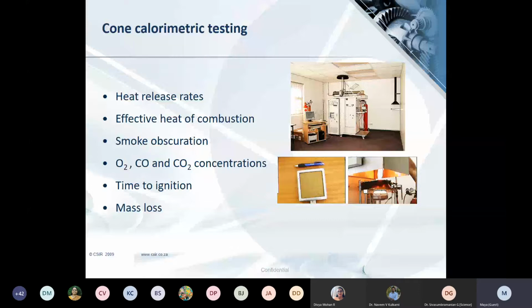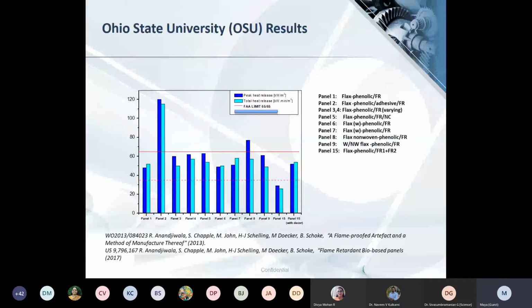So these are the flammability results from the OSU testing. And this graph shows the peak heat release and the total heat release of the different panels. And the FAA limit, which is the Federal Aviation Admin limit, is 65. So for a material to be qualified to be used in aircrafts, the peak heat release and total heat release should be equal to or less than 65.